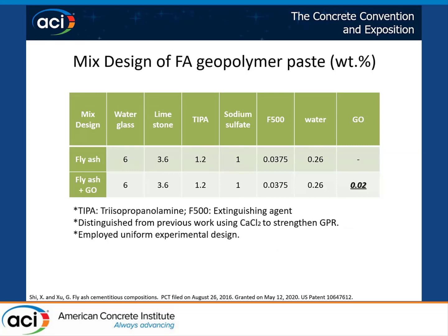No, that's fine. With geopolymer, there is the issue with shrinkage. So, do you have any experience with shrinkage when you add GO? Very good question. Actually, I'm not sure why Zhipeng didn't present that. In one of his published papers, this is actually intended to serve as an alternative to expansive cement. In other words, this one actually expands a little, there's no shrinkage. And the level of expansion could be customized based on the mix design. So the shrinkage issue goes away.